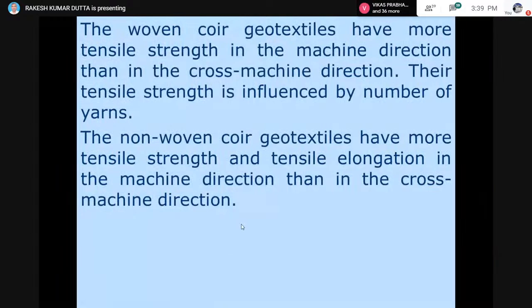The woven coir geotextiles have more tensile strength in the machine direction than in the cross machine direction. The reason for this is that there are more yarns per meter length along the machine direction in comparison to the cross machine direction, because their aperture size may not be uniform in both directions. On one side it may have a smaller aperture value, on the other side a larger one. So the number of yarns per unit length along the machine direction could be more, and fewer per meter length along the width of the roll. Right? So the tensile strength is influenced by the number of yarns. That is the main conclusion.